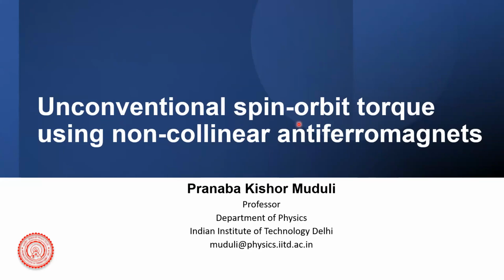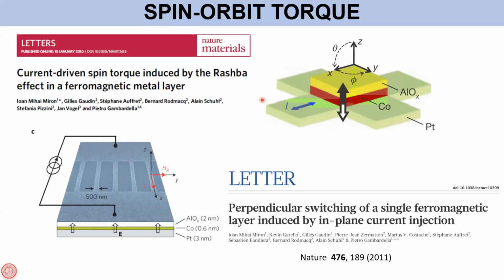So I would mainly talk about, I changed the title a little bit because there are two "non"s. I made the first one unconventional spin orbit torque using non-collinear antiferromagnets. I'll start by very briefly discussing what spin orbit torque is. Spin orbit torque basically started around 2010 and 2011, when Gambardella's group showed that with a bilayer structure consisting of platinum and cobalt, you can drive a domain wall by means of current, or even switch the magnetic layer by passing current. This led to the starting of the field of spin orbit torque.